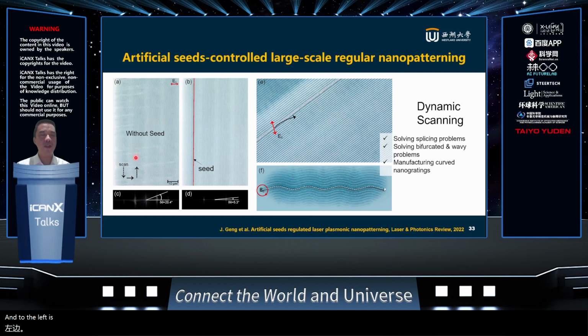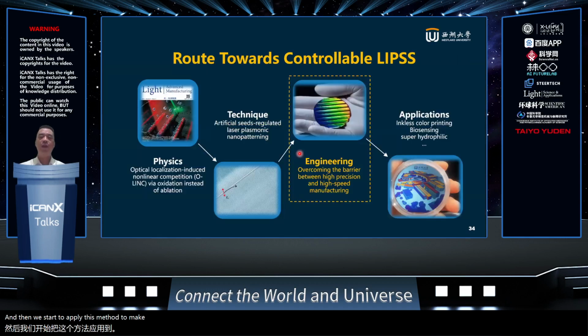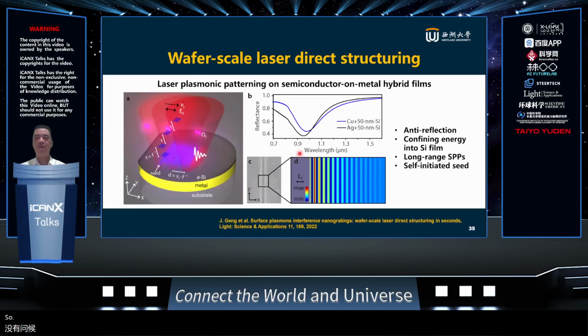To the left is without seeds. We can still do large-area gratings, but they are not so regular. But if we have a seed more than 100 micrometers long written first, the generated grating is unbelievably beautiful. We can even make a special seed like this, with curved lines, and then we can make curved gratings, again very easily. So we solved a lot of problems using this technique. Then we start to apply this method to make extremely large, high-precision nanogratings, and I'll give one example.